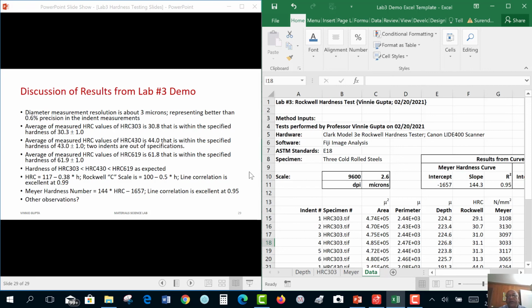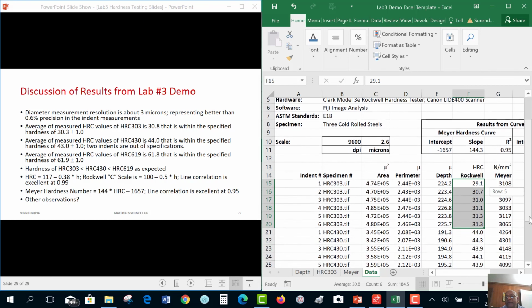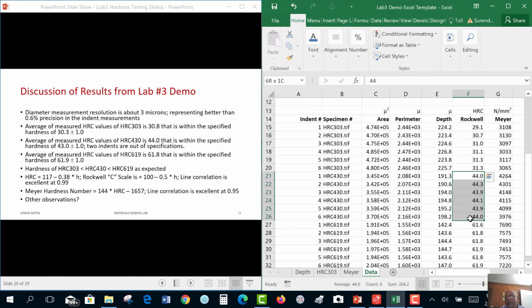Now the averaged measured value in HRC for 303, so I averaged these values, was 30.8. It's within the range. For the next sample, 44 is in the range, except that notice 2 indents are out of spec. Average is okay, but 2 indents are out of spec. For 61.9, our average value is 61.8. All of those indentations are in spec. And of course, we found that hardness of 303 was smallest, then least cold worked, middle cold worked, most cold worked. So we expected that.